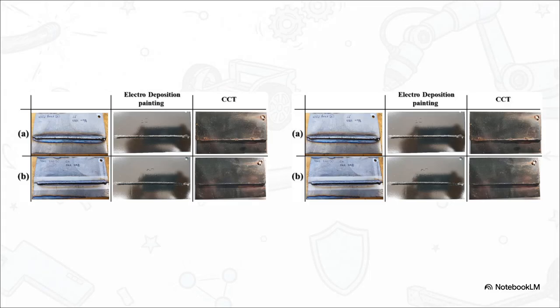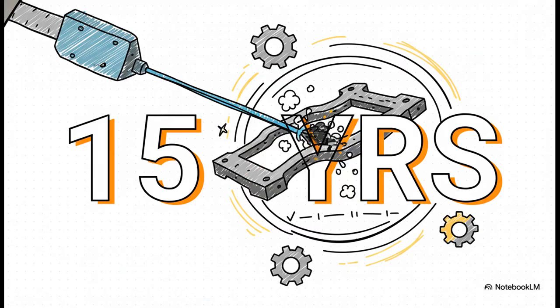And the results are absolutely stunning. Just look at this. After 95 cycles inside that corrosion chamber, the sample that was not laser cleaned is a complete rusty mess. But the laser clean sample? It looks almost pristine. The visual evidence here is just undeniable. So what does this all mean in the real world? It means the laser-cleaned steel officially passed the industry's 15-year corrosion durability standard. This technology doesn't just clean a surface, it fundamentally extends the life of a critical part of the car.